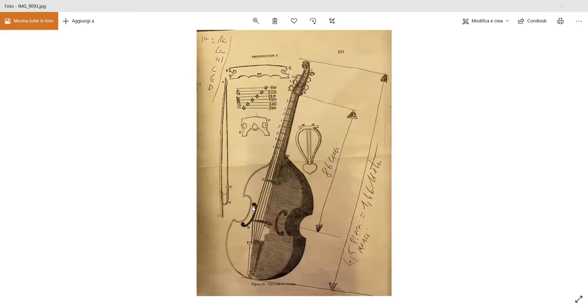I mean, 64 up to 63, 67. We did the average around 68, 70. So, by proportion, we can calculate that 48 gives minimum 2 millimeters and 60 maximum 3 millimeters, with 50 guts minimum 2.65 and maximum 3.06. 48, 50, you know, is almost the same. And 60 guts produce minimum 2.90, maximum 3.35 millimeters. And the average of all these indications was around 3 millimeters diameter for the sixth string.